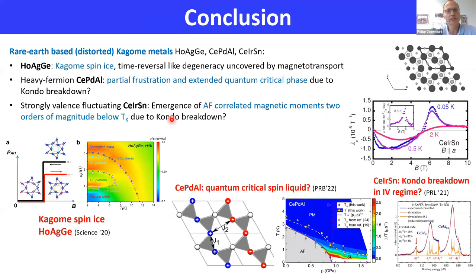So I discussed 3 different members of this family of 4f electron-based Kagome magnets, which have also conduction electrons, so which are metallic. And in case of holmium silver germanium, I showed you that the different magnetic phases, which we uncovered by neutron scattering, all fulfill the Kagome ice rule, and that actually the ground state is exactly the same as predicted by theory for the 2D Kagome spin ice.